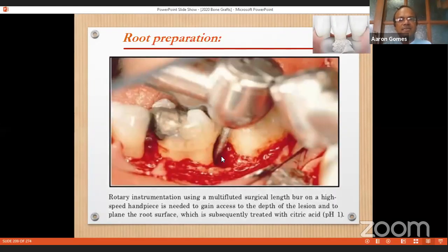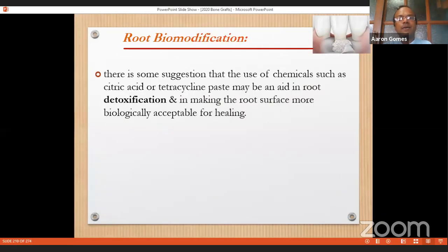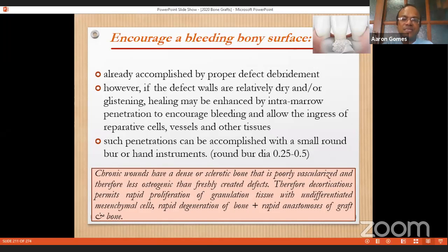So you've seen a fine bur, but do this very, very carefully at slow speed with good irrigation, such that you do not gouge the tooth surface. You will then do root preparation with treatment of one freshly prepared pH 1 citric acid, or you can detoxify also with tetracycline or use fibronectin solution. You must encourage a bleeding bony surface, but not too much bleeding. If the bleeding is too much, you have to control it, otherwise your graft will wash off.